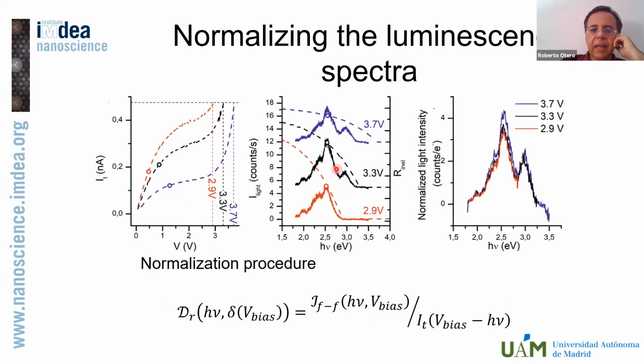Therefore, we have here the optical spectra for this tunnel junction recorded at 3 different stabilization voltages. We have here the IV curves recorded at the same stabilization voltages. So I take these IV curves, I flip them back in energy, I shift the zero to the applied bias voltage, and the first thing that you can see is that indeed the overall intensity scales with the tunneling intensity that you would obtain by doing so.